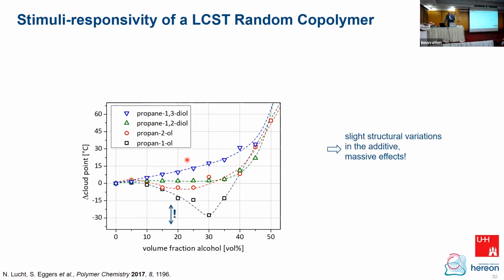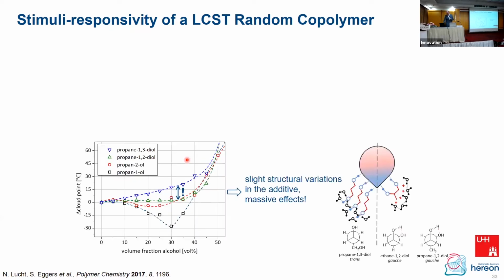presented to you. You can play with the structure of the alcohol. So here you see just propanol, so to say. So single functional propanol, so n-propanol, propan-1-ol, propan-2-ol, and we have also the difunctional propanol, so propan-1,2-diol or propan-1,3-diol, and depending on how these structures look like, you get a quite strong effect on this co-non-solvency effect here. Okay, and yeah, this is just an example here of propan-1,3-diol and propan-1,2-diol, which behave quite different here in terms of the solubility.